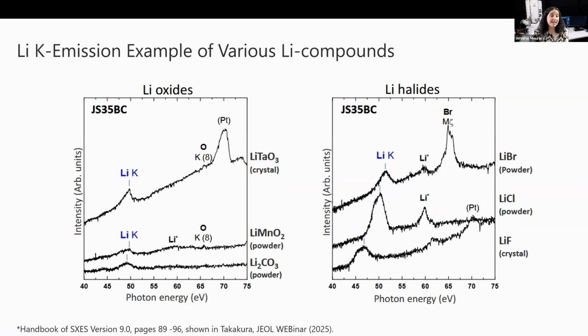And here we can see SXES spectra for a few other lithium compounds. It's possible to detect lithium in lithium carbonate, lithium tantalate, as well as lithium manganese oxide powder, shown here. Also, lithium is possible to detect in some halides like lithium bromide, lithium chloride, and lithium fluoride. And we're currently conducting more studies to see which lithium compounds allow for lithium detection using this method.